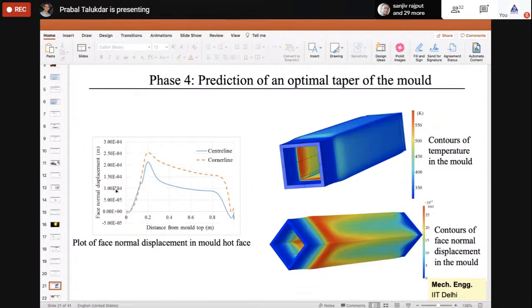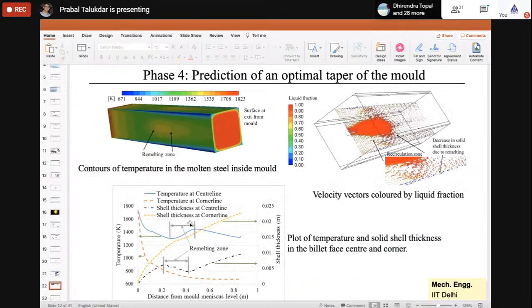That is shown graphically here also. The center line deformation is a little less than the corner line, and from the meniscus to the exit of the mold, these deformations are shown. All these deformations are not the same everywhere, right? At the meniscus it is 0 because it is the beginning of the mold, and gradually it increases, and after that it starts decreasing gradually, right? That is what you can see from this diagram, and based on that we have predicted the top taper of the mold.